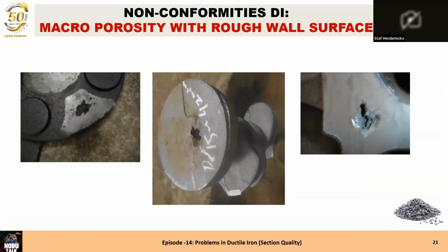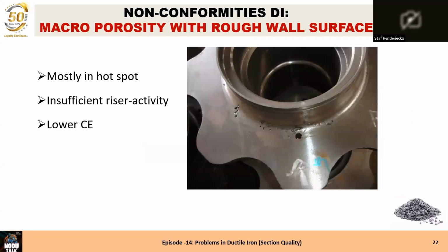Here you see some real porosity, macro porosity with rough wall surface. This mostly happens when the carbon equivalent is lower than 4.3, but can also happen somewhat higher. But a rough surface is mainly when the carbon equivalent is less than 4.3. Here you can see that it is many times located in a hot spot, because the hot spot is the last solidifying area, and if there is no compensation, then we have, of course, that porosity. It is due to insufficient riser activity. If the riser does not deliver feeding metal until the last second, it will lead to a porosity. And it's mostly with a lower CE, lower than 4.3.